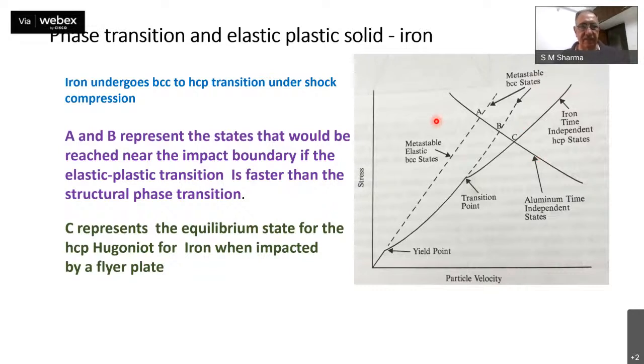So as I said, A and B represent the states that will be reached near the impact boundary if the elastic-plastic transition is faster than the structural transition. Incidentally, if the structural transition is faster than this, obviously this won't happen, and then the sequence will change. So C represents the equilibrium state, which is incidentally the HCP phase at high pressure. It represents the hexagonal close-packed Hugoniot for iron when impacted by the flyer plate.